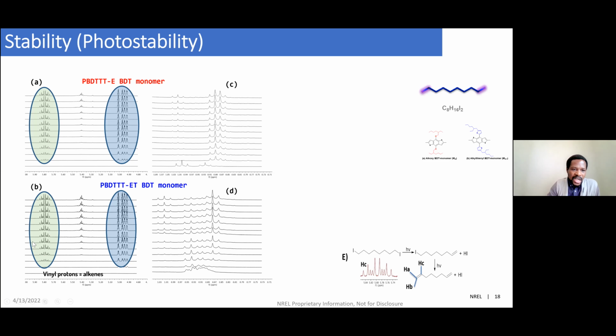And the peaks in this chemical shift range, 4.8 to 6, belong to the vinyl protons, which are known to be part of the alkenes. So these protons around the shift of 5.8 belong to the second hydrogen or proton on the alkene chain. And then the chemical shift around 4.9, which also increases in intensity, belongs to the terminal vinyl protons that are labeled here HA and HB.